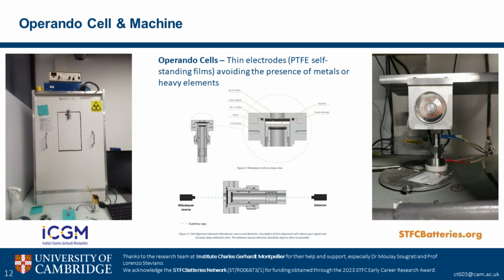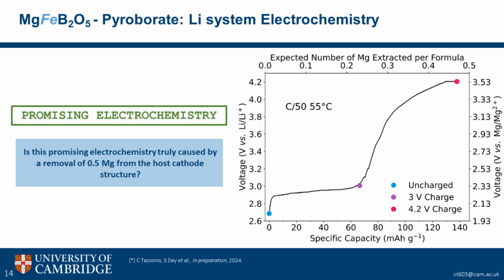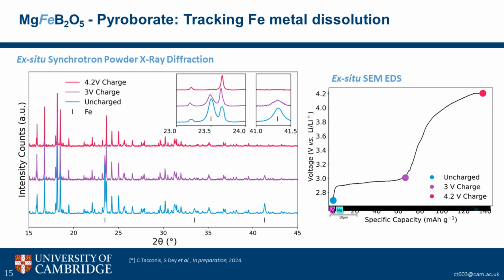So now back to my work and how the Mossbauer was useful in determining what was going on inside our cathode material. Just as a reminder, this was the promising electrochemistry that we were looking at. And what we, again, were looking to find out was whether we were removing magnesium from the host cathode structure. So at the very early stages of the research, we started with some ex-situ analysis. So we took some coin cells, cycled them, took out the cathode powders, and sent it to a synchrotron. And we collected 3 main stages of the charge at the end of the 3-volt plateau that we see, and then at the end of the 4.2-volt charge with the CCCV.